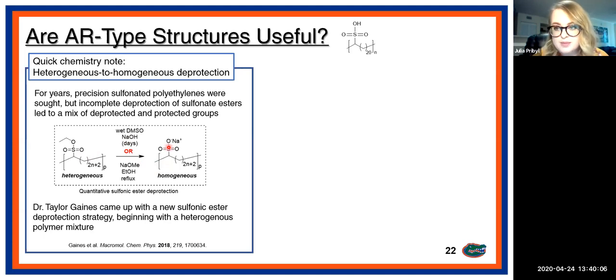So as the polymer becomes more soluble, that gives access to more sulfonic esters that can be deprotected. So it's sort of like a self-amplifying type of system where at the end, you get quantitative deprotection of the sulfonate groups. If you go to read this in the literature, it's in this paper here, you'll actually see that it was changed to using sodium methoxide and ethanol. And the reason for this was mainly because the DMSO was a little bit difficult to remove after deprotection.